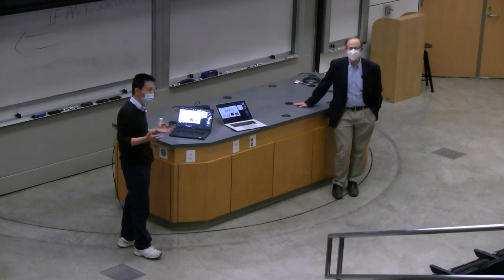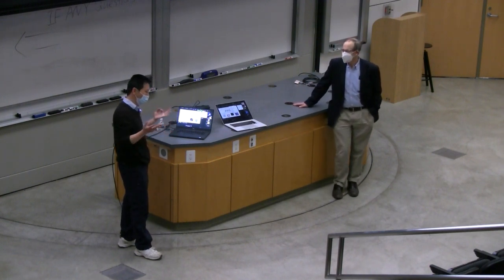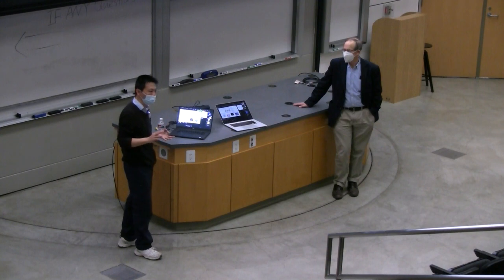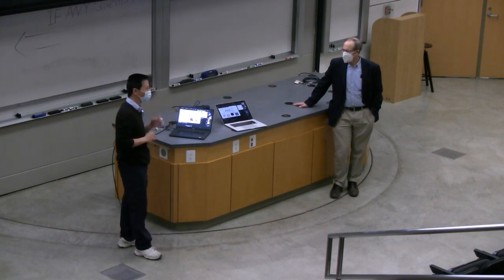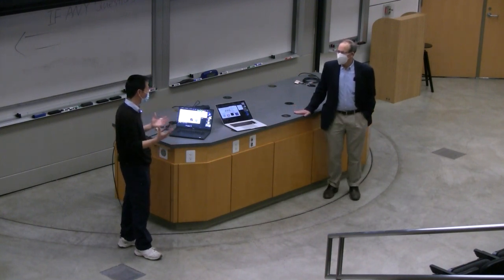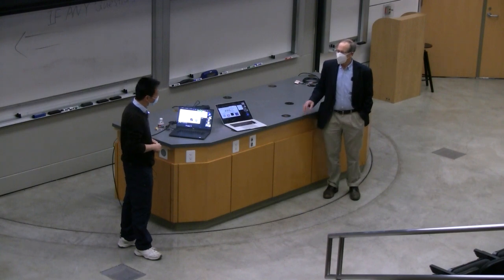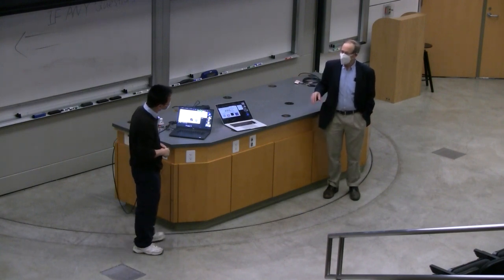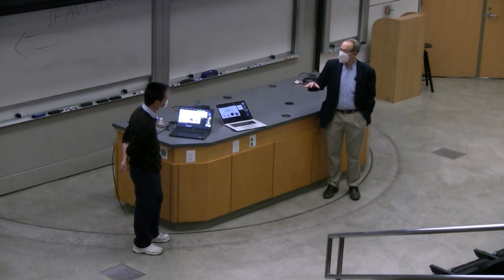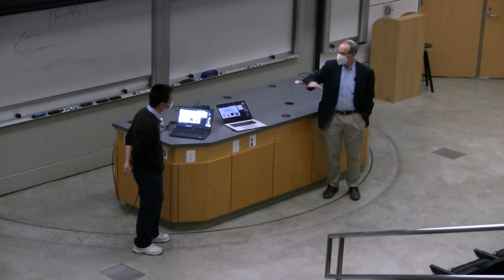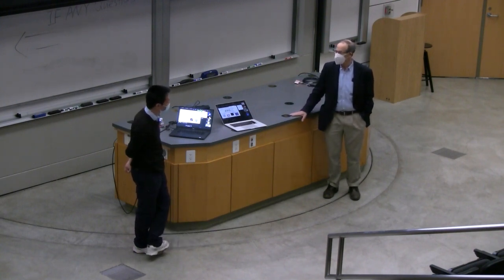With a 2D system, the good thing is you can use a scanning probe to see them pretty well. In a 3D system, it is actually harder to see the lattice. But that gets to the second point. Clearly there's some role of inhomogeneity, because your image is fixed, right? If it were a totally ideal system, it would probably be mobile, basically, to some degree.